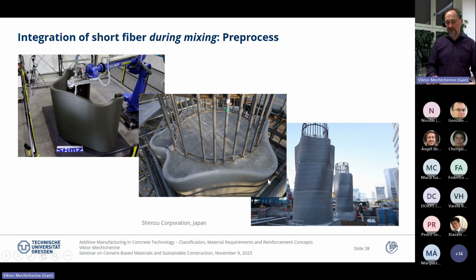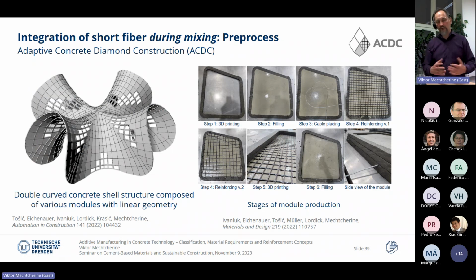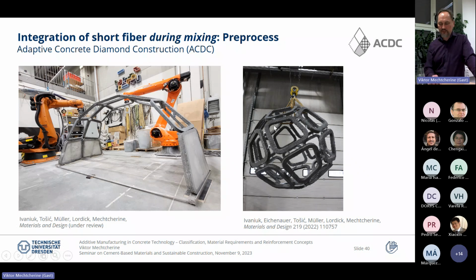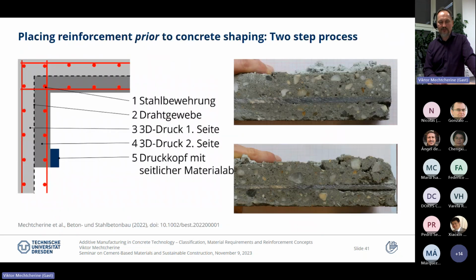You combine here nice geometry, which is also of structural importance, and also very advanced technology. We use this approach also for producing some fancy shells made of panels, or rather elements which are flat. So it's all linear geometry, but by putting these elements together, you can produce all kinds of curvatures. And this is a multi-step process. We first print the edge, then we fill in some flowable concrete, put in some reinforcement, other textile which is already ready-made, or we deposit yarns and produce the textile in situ, and then some steps can be repeated until we complete the production of these elements. We have one or two demonstrators to show already, and this is ongoing work. Some publications are submitted and you can read them soon enough.